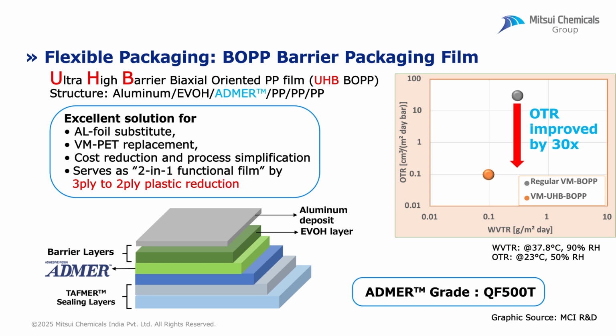As can be seen in the slides, Admer provides excellent adhesion between oxygen barrier EVOH resin and PP resin, which helps to complete high barrier structures and enables 3-ply to 2-ply laminate conversion. This results in reducing virgin plastic consumption.